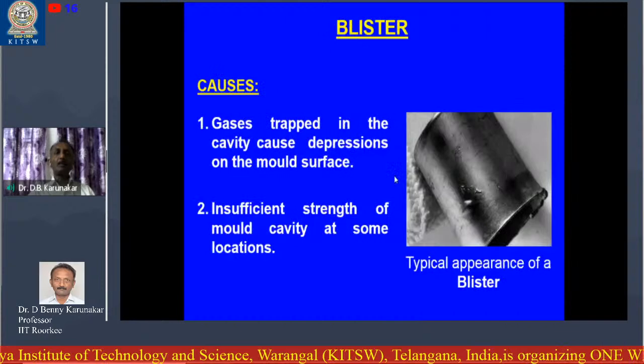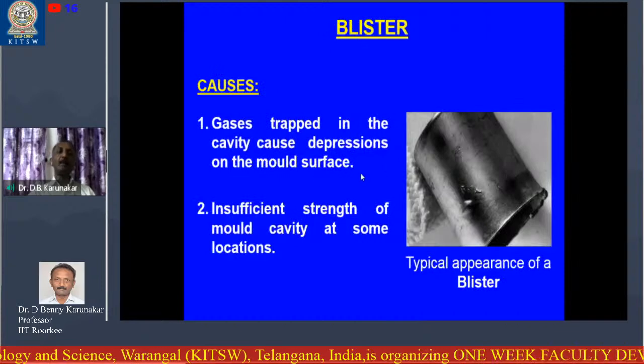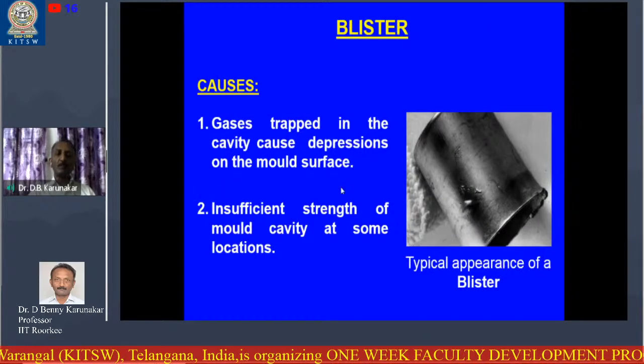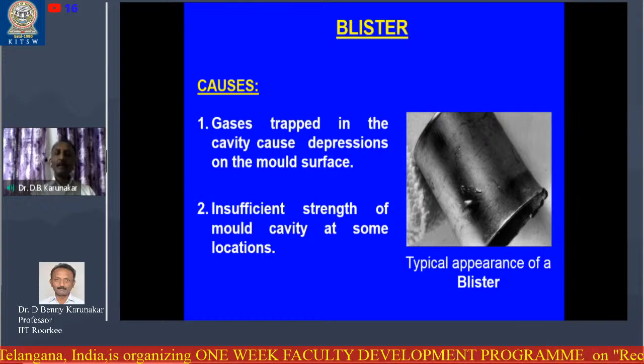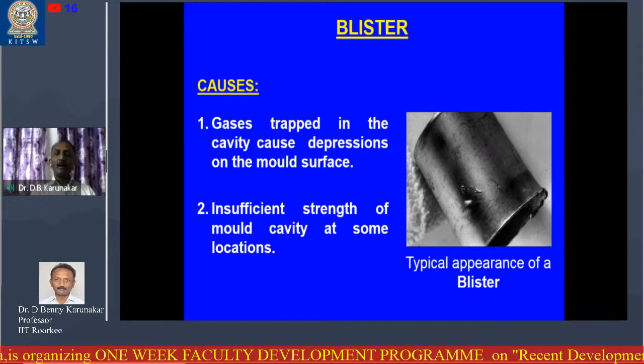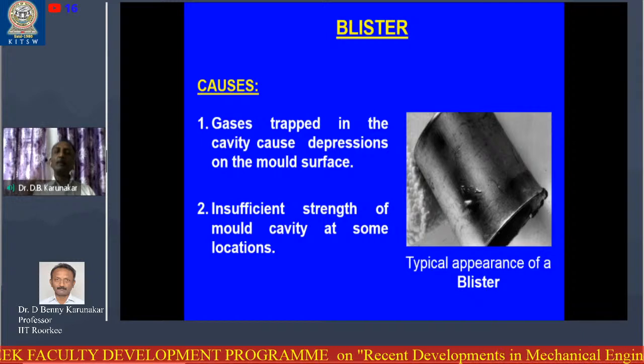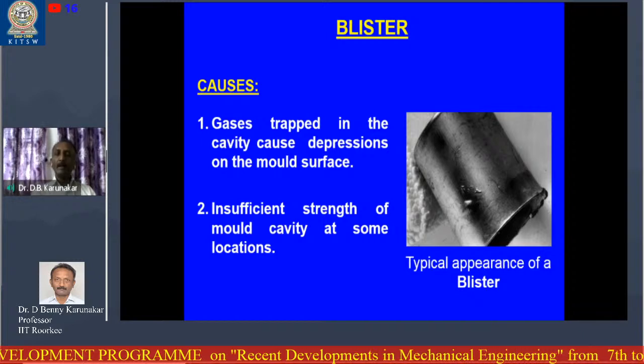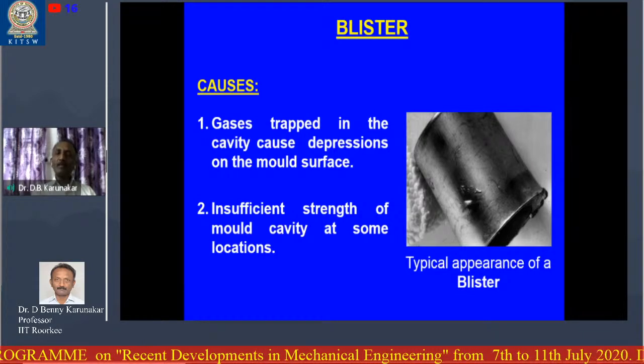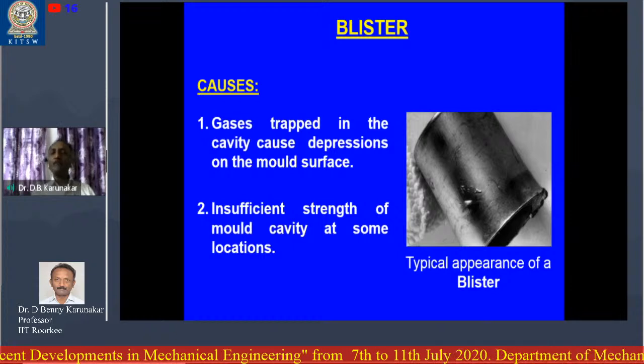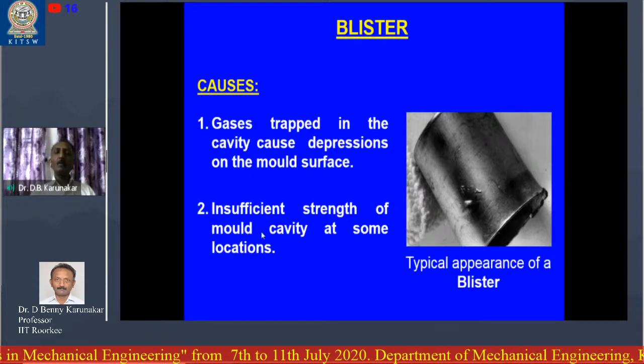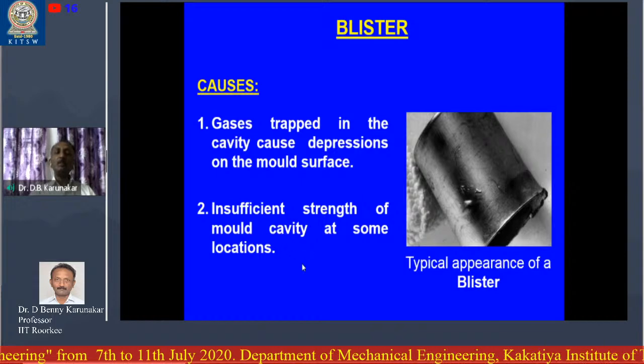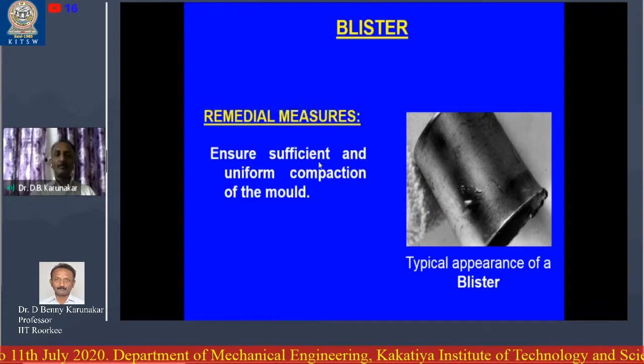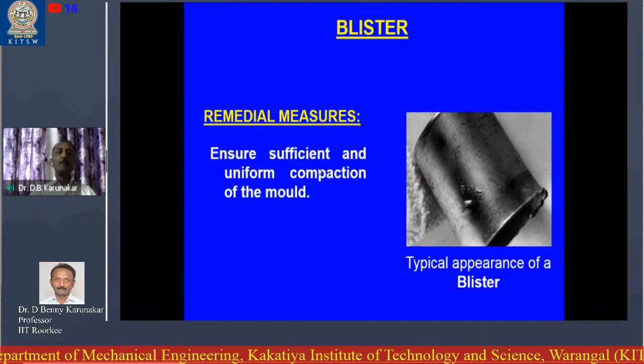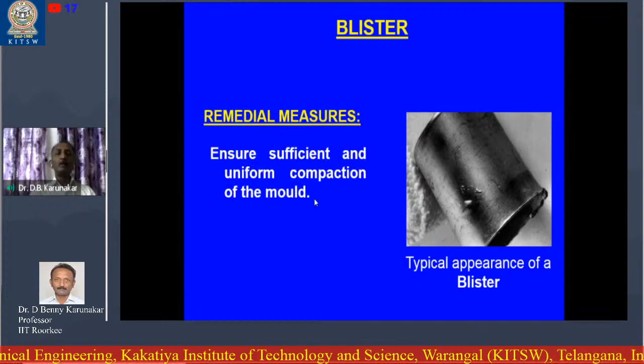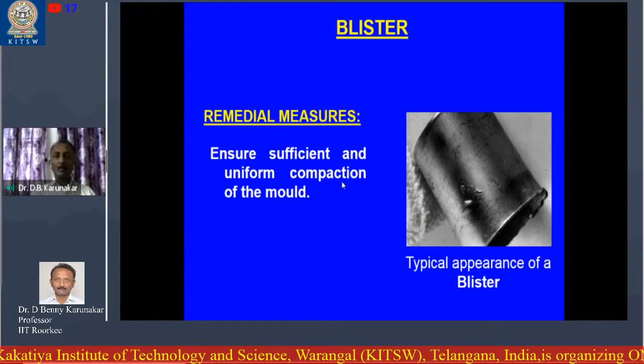What are the causes? Gases trapped in the cavity cause depressions on the mold surface. Means there are gases in the cavity, and they are able to cause depression on the mold surface. Why? Because the strength of the mold is very poor. Means the compaction is not sufficient. So there is insufficient strength of the mold cavity at some locations.